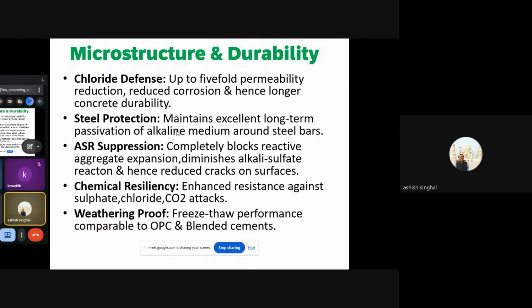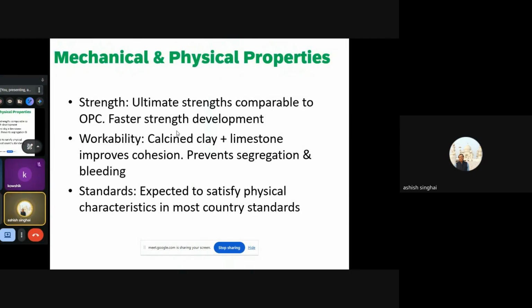Chemical resilience, enhanced resistance against sulfate, chloride, and carbon dioxide attack. Again, it will make your concrete a durable one, and weathering proof. So freeze-thaw performance in areas where the temperature goes to as low as -10, -15 degrees Celsius is comparable to OPC and blended cements. So these are a couple of the advantages.